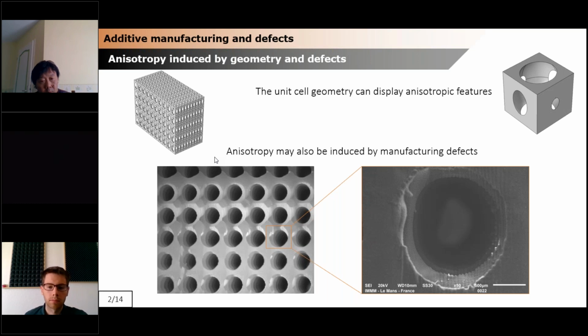But in fact, when you look closer with a scanning electron microscope, for example, you will see corrugations that appear. Basically what it does is that it induces anisotropy in the porous layer, because you have this layer by layer surface roughness, which actually increases the fluid solid interface, but it's also direction wise. So you have those two anisotropic properties. One is purely related to the design of your unit cell and the choice of it, and the other one is purely linked to the inherent defects of the additive manufacturing technique.